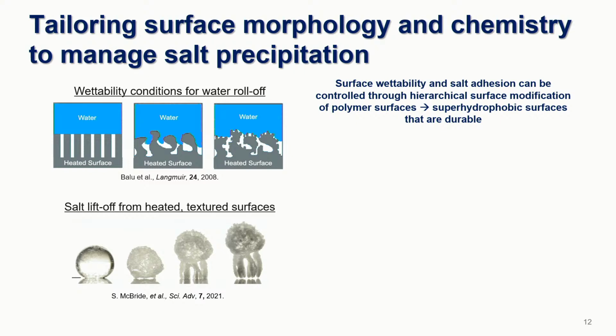And so really we can do this control of the surface morphology as well as the surface chemistry to get the kind of wettability and adhesion behavior that we want. And we're doing this by creating superhydrophobic surfaces. A lot of work has been done on this topic in the past, but the biggest challenge has been that the surfaces are not durable. So after you use them, especially in a salt environment, you see that those surfaces over time lose their superhydrophobic behavior.